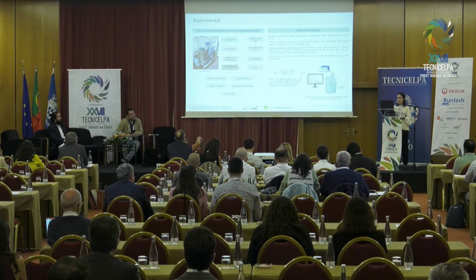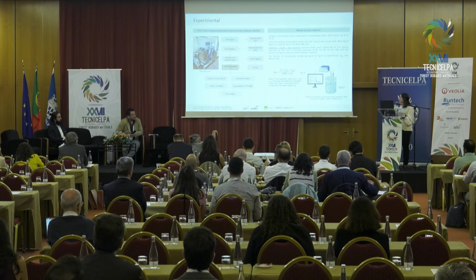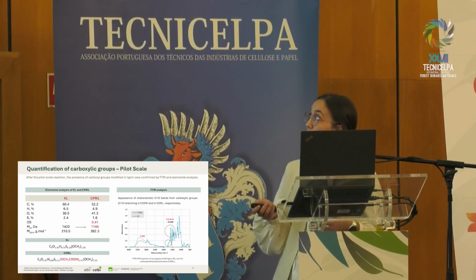Having those optimized conditions, they were applied at the pilot scale to prove if it's scalable and the repeatability of this process, and the modified lignin was further characterized by elemental analysis, thin analysis, and other analysis. And we also tried to understand the metal sorption behavior of this modified lignin in comparison to the pristine lignin, focusing on cadmium, copper, and mercury ions.